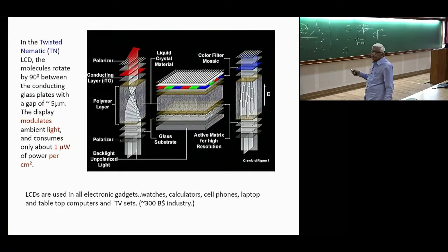And instead of magnetic field, of course, you use electric fields. So this is a typical way the display works. This is called a twisted nematic liquid crystal display. What you do is, instead of having two surfaces where the rubbing is parallel, the top surface has the orthogonal rubbing direction. Then the elastic response necessarily rotates the director by pi by 2 in the ground state.